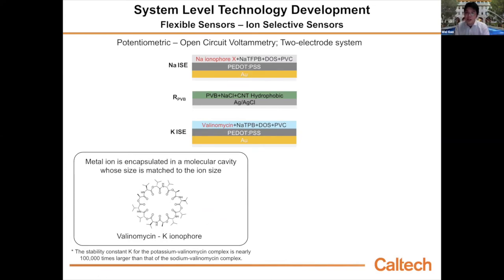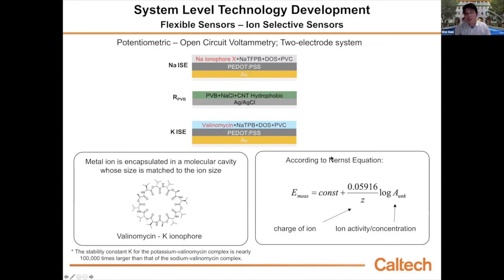If you put this ion selective sensor in a solution that contains potassium ion, the potassium will enter this ring and set the voltage of this ion selective electrode. We are measuring essentially the voltage difference between the ion selective electrode and the reference electrode. According to Nernst's equation, the sensitivity is 59.16 millivolt per decade of concentration. The measured voltage has a log-linear relationship with the ion concentration. This is how we monitor ions.